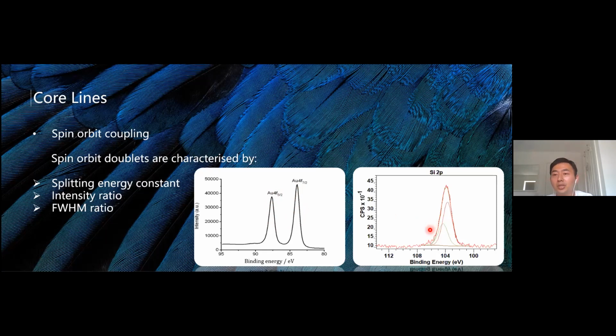And this silicon 2p looks like a single peak, but actually, because the splitting energy constant is very small, it's just below 1 eV. So therefore, we should always remember that there are actually two peaks with a 1:2 ratio, which consists of these silicon 2p peaks.